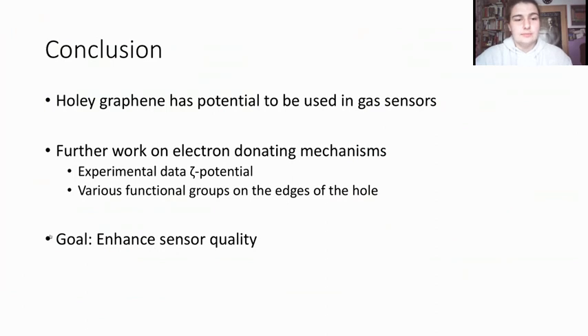So we could show that holey graphene with gold clusters has potential to be used as a gas sensor for hydrogen sulfide gas. Further research will be conducted on electron donating mechanisms between the hydrogen sulfide molecules and functional groups on the graphene hole. How much the system attracts the negative charge could be compared to experimental data of zeta potentials of the model. And we could also see how different compositions of functional groups on the hole affect these. And all these may be possibilities to enhance the sensor quality, which is the ultimate goal of this research. And thank you for your attention, and feel free to ask questions now.